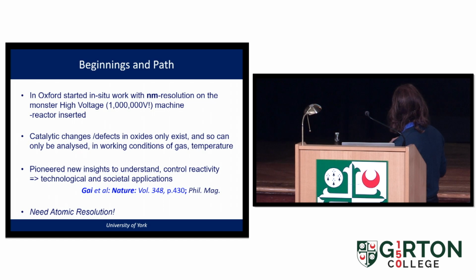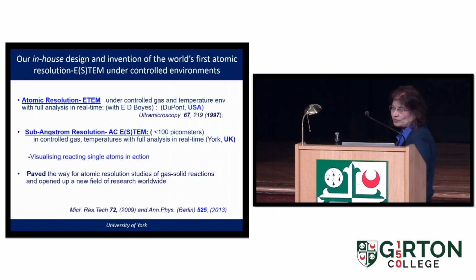But nanometer resolution wasn't good enough, so we needed atomic resolution before anybody else. We wanted to be the first. So that's what we did. We built the first atomic resolution microscope, we were at DuPont at the time, under controlled gas and temperature environments, to look at the reactions in real time as they're happening, and also analyze them at the same time. And in York, we have then added both the TEM and the STEM configurations, as I mentioned earlier, and also what's known as aberration correction. This is correcting aberrations of the electron lenses. I'll come back to that a bit later. And this allowed us to look at single atoms in action. These developments actually paved the way for atomic resolution studies of gas-solid reactions and opened up a new field of research worldwide. So if you take some risks, it can pay off.